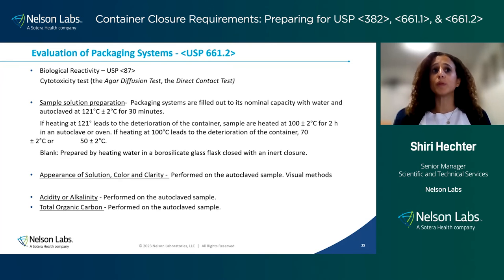And in the sample prep, we will need to prepare a blank, and the blank will be prepared by heating water in a borosilicate glass because it's inert. And then sample and blanks are both compared during testing to see the differences between the blank, which is going to be water that assumes that there's no extractable or any material from the glass leached to it, and the sample prep, which is the actual packaging systems.